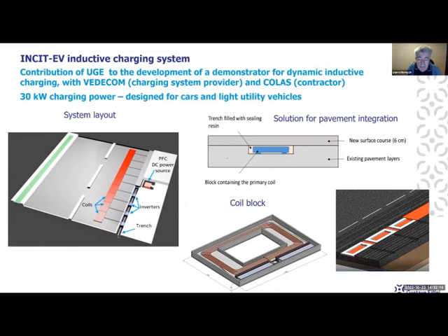And so the idea is to use it on existing pavement: to create a trench in the pavement, to install the blocks in the middle of the pavement, to seal them with a special resin which will ensure a good bonding with the asphalt layer, and then to cover it with a thin new surface layer. Here, on the bottom right, you can see the layout of the system in the road before it is covered by the surface layer.